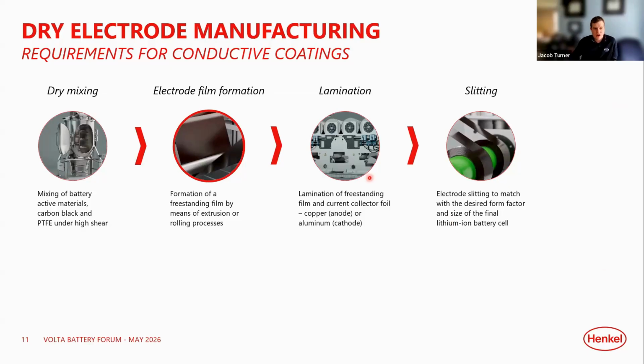Okay, so when we get into dry electrode manufacturing, this might be something that's a little newer for people. It hasn't been around for quite as long, but the core difference is in that first part of the electrode manufacturing process. Instead of a slot die slurry based coating, it's a dry mixing of powders, usually some sort of freestanding film formation or perhaps a spray of those materials. And then it goes through a lamination and slitting behavior.